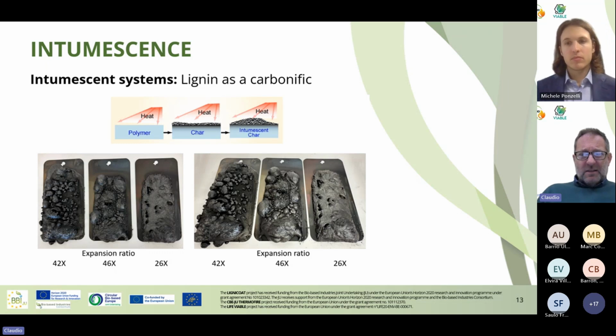There are some hints in the literature that it might do so. We have done a number of tests. Actually, lignin alone can give some degree of expansion, but not much. But if you add some additional standard carbonific or some blowing agents, then you can achieve an interesting expansion ratio, up to 40-something times. Aitor said that you can have expansion in tumescent coatings up to 100 times.